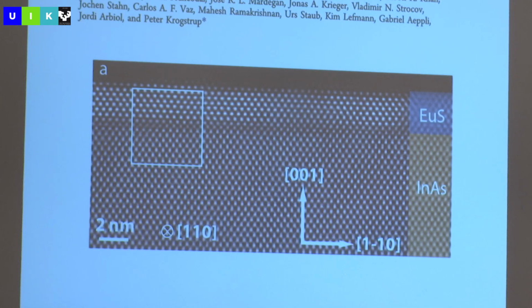Our approach was to take the same idea that we had when we started growing the epitaxial aluminum on semiconductor and try to do the same thing again with these ferromagnetic insulators. And the shocker is it worked. It's a miracle enough that you've got epitaxial growth of a non-lattice matched aluminum on top of an indium arsenide semiconductor. But to get epitaxial growth of europium sulfide on top of indium arsenide with aluminum on top of that seems borderline crazy, except here's the data.